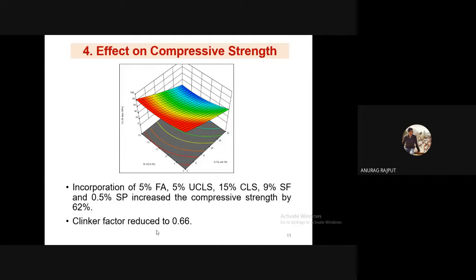If we talk about compressive strength, we know that with the addition of fly ash, 28 days compressive strength decreases. So a very low level of fly ash was used here, with uncalcined limestone at 5%, and 15% of calcined limestone. This is the maximum usage of calcined limestone we have used. And 9% of silica fume and 0.5% of superplasticizer increased the 28 days compressive strength by about 62% as compared to control mortar.